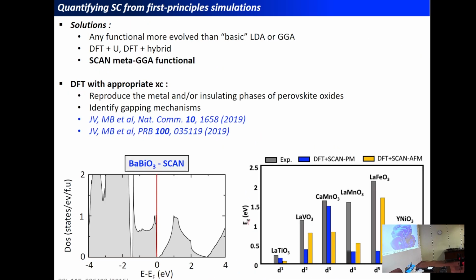So the solution to correct this self-interaction error is to use functionals that are more evolved than the basic local density approximation or generalized gradient approximations, which ultimately yield metallic systems when they are supposed to be insulators. For that, you can use DFT plus U or DFT plus hybrid, which are the highest level we can do in DFT. But now there are meta-GGA functionals, which are intermediate between GGA and this type of approach, which can reproduce the insulating character, for instance, of barium bismuthate.